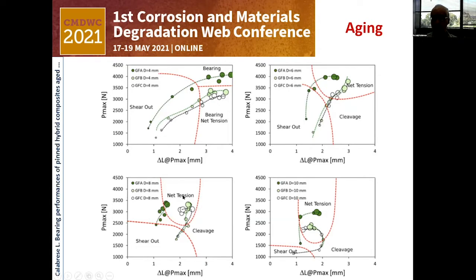for the samples that are characterized mainly by bearing fracture, we see that the unaged one has a higher maximum stress, but the other two plots do not evidence a shift to higher displacement. Instead, when we have a premature fracture mechanism such as net tension or shear out, we have an evident shift of the curve to higher displacement, indicating that the aging influences the stress-strain behavior of the joint.